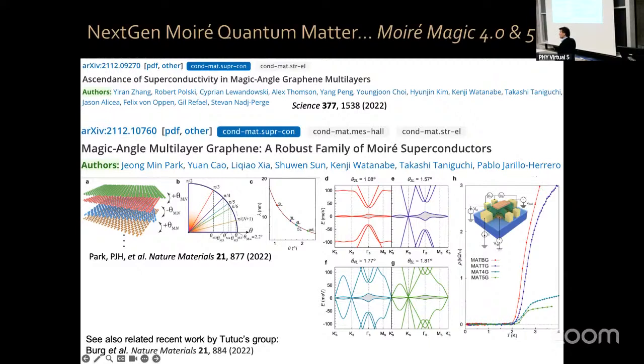They increase the magic angles, but they increase on this circle, so they reach saturation. If you're curious, you can check this paper. There's actually something related to the golden ratio in the way the angles go, which is very interesting. But there is saturation—the Moiré patterns, the Moiré wavelengths, go to shorter and shorter distances, but they saturate, like this, for infinite layers.